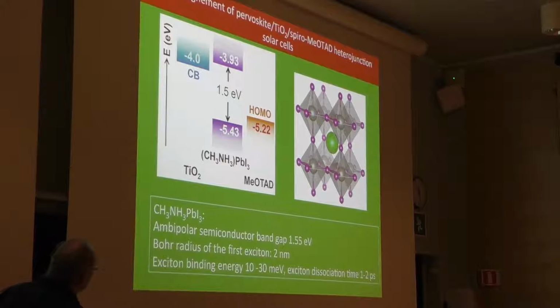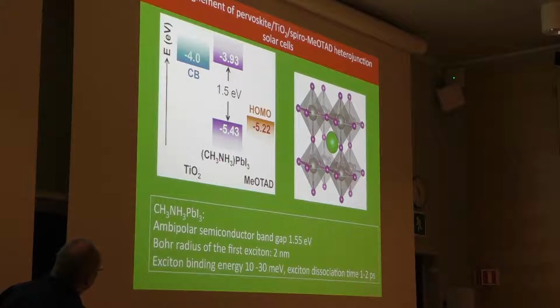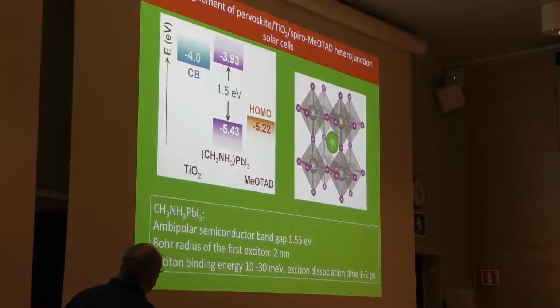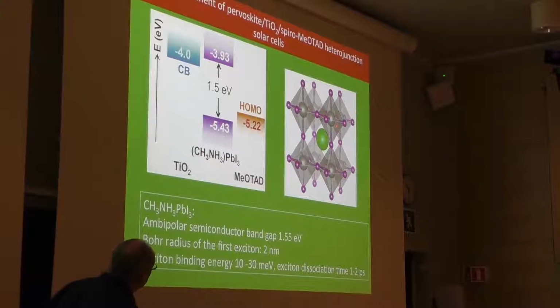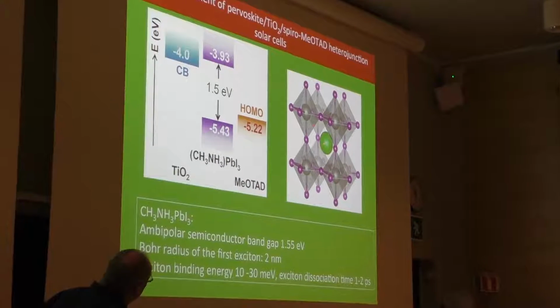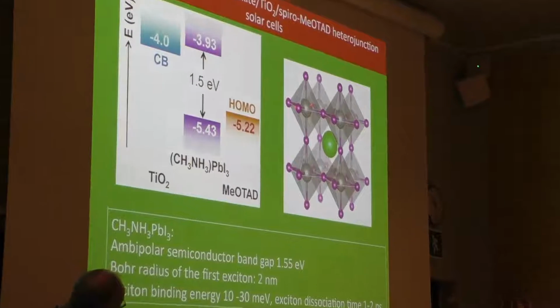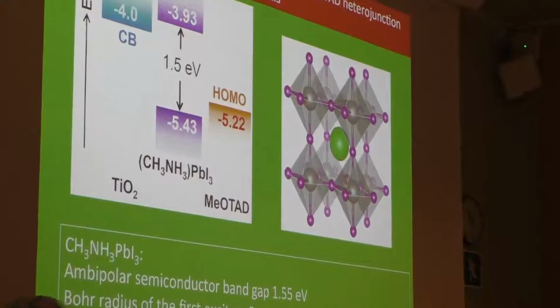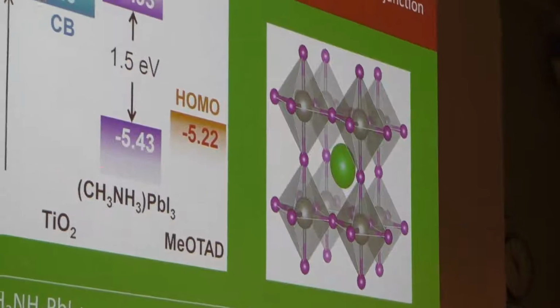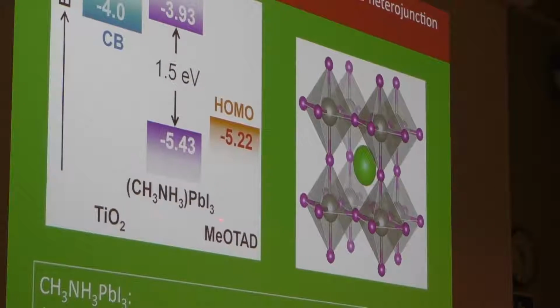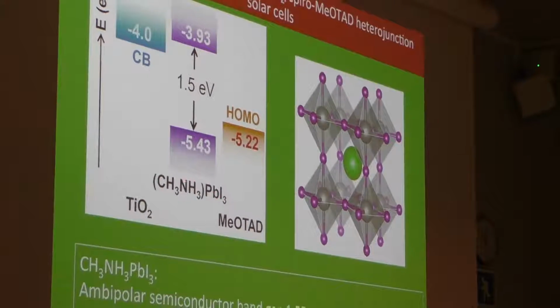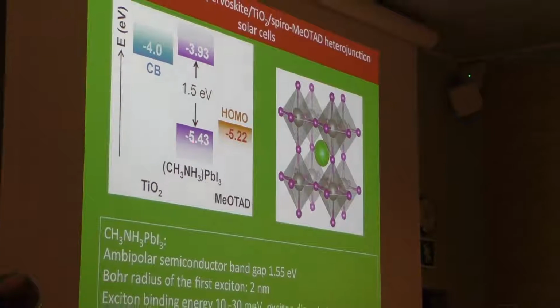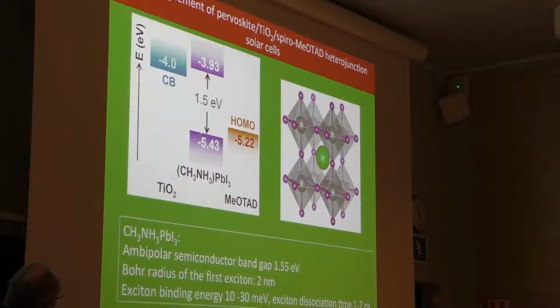Perovskite is organic-inorganic. This is the classical one. It's a methylammonium cation, it's lead, and it's a halide like triiodide. This is the perovskite structure. You have the cation in the middle here, the lead here, and then you have an octahedron of the halides like this. So that's the perovskite crystal structure. It has a good band gap, which you can tune by substituting the halide and the cation. So this classical one is about 1.5 electron volt.